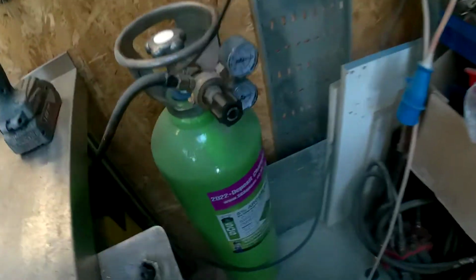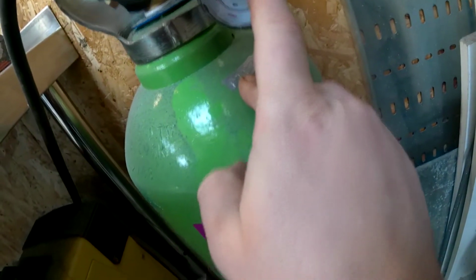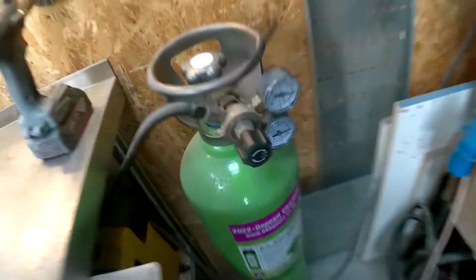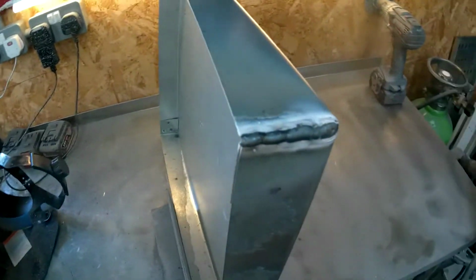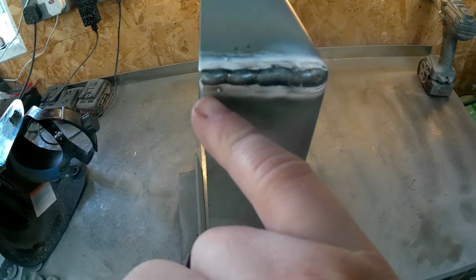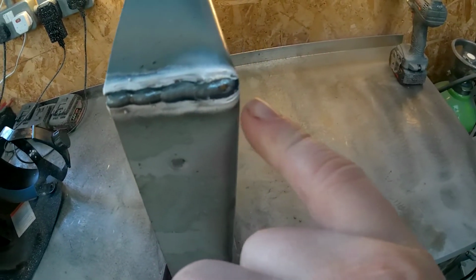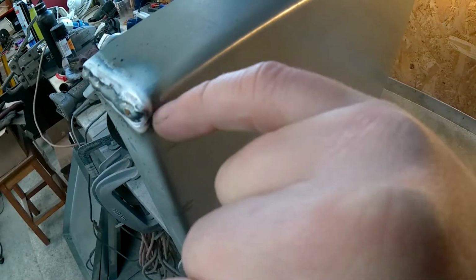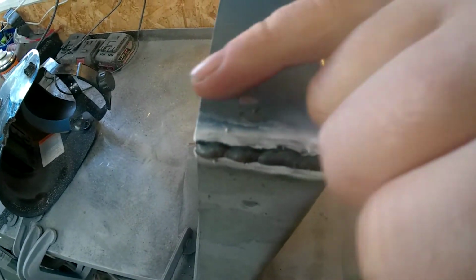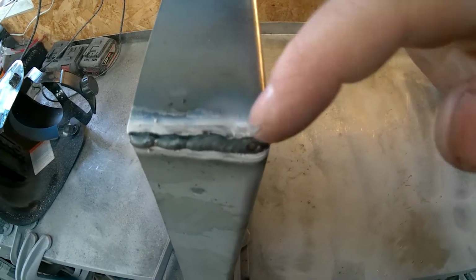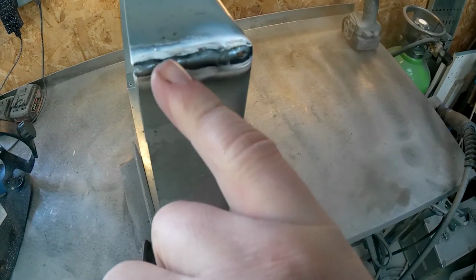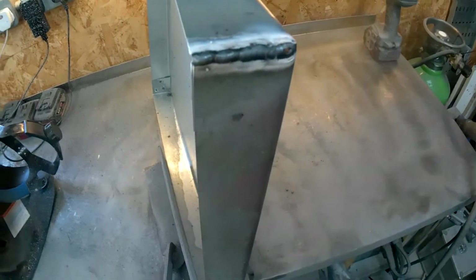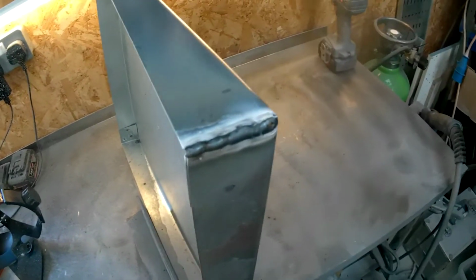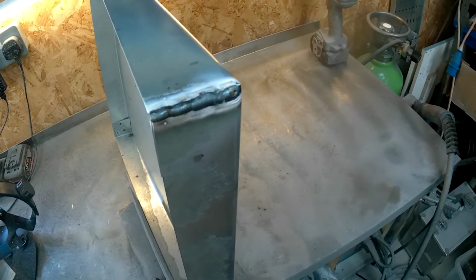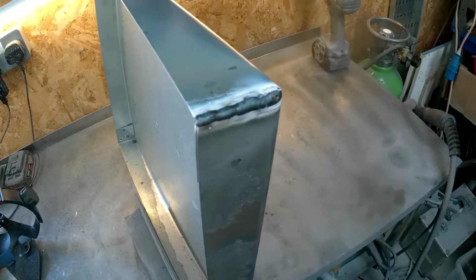So then I jacked it up to about 12 litres per minute, and then we did the other corner, and if you look here, we've got the white spray off all down the side and round. There's a tiny bit of bluing, but no real black contaminant, no black marking really, all the way along, and the weld is much tidier. It's got a nice pooling, a nice carriage all the way along, and that's the only thing I changed between the two, is jacking up 2 more litres per minute. So it shows you what a difference that can make.